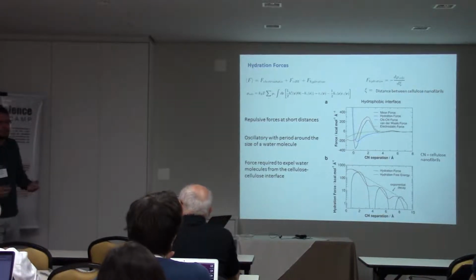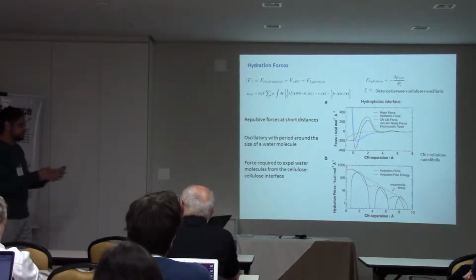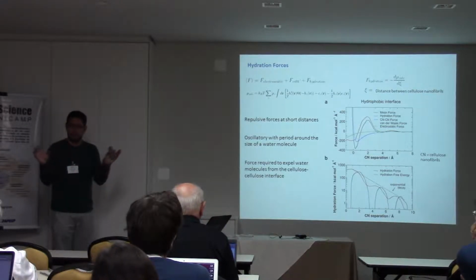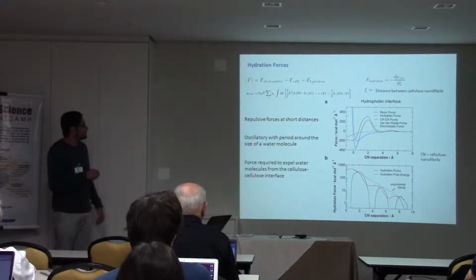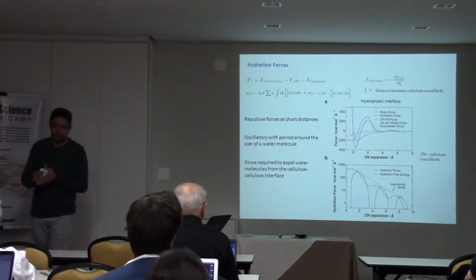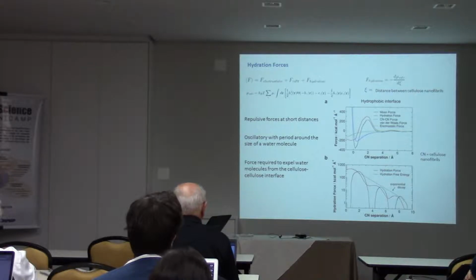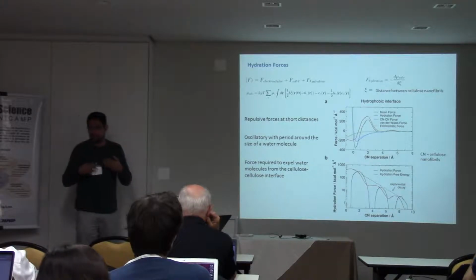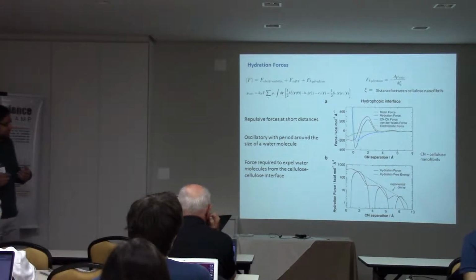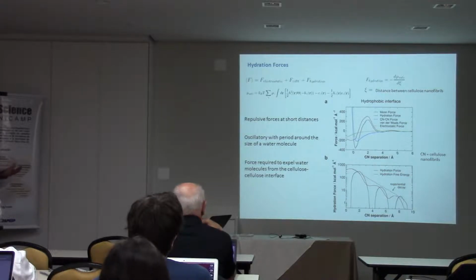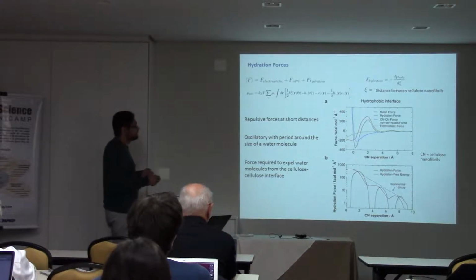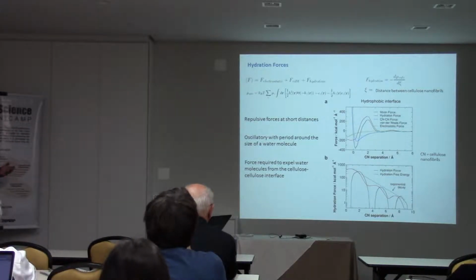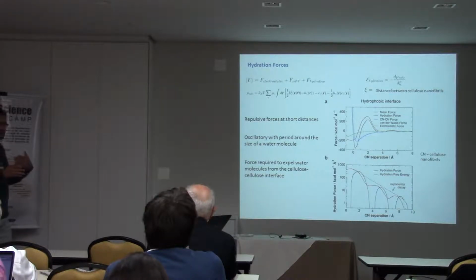This is a solvent effect, which comes from hydration. So if you don't have water and you approach two cellulose fibers, they will interact with electrostatic and van der Waals forces only, and they will aggregate. But when you have the solvent, it might prevent this aggregation, or make it more difficult. So this hydration force is computed from the solvation free energy, right?